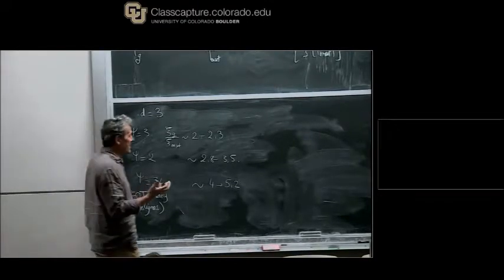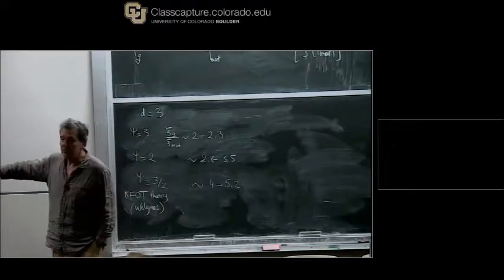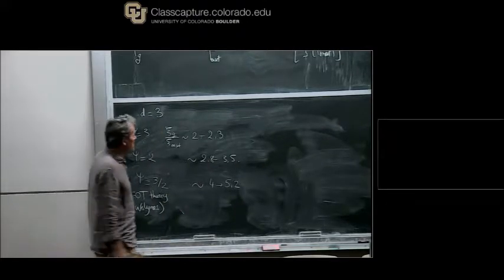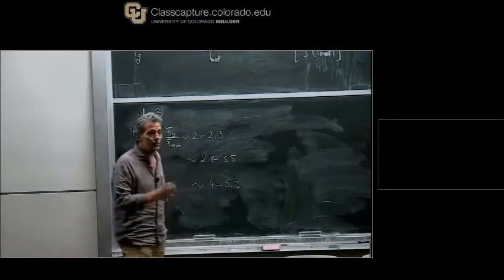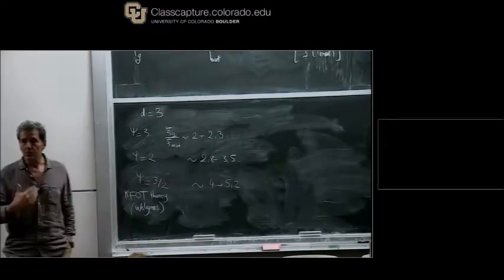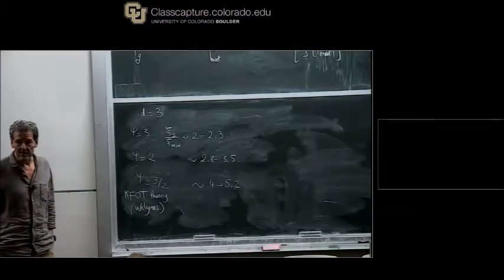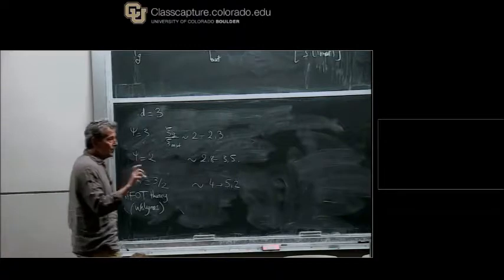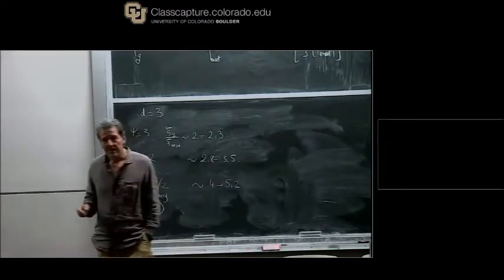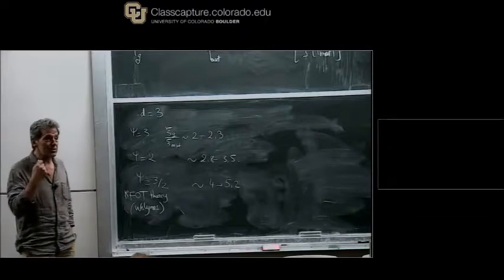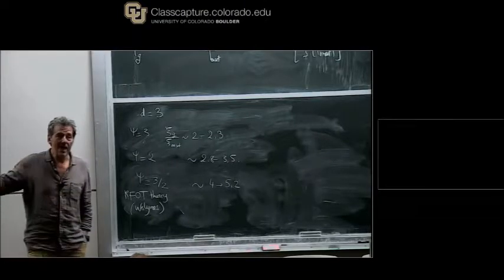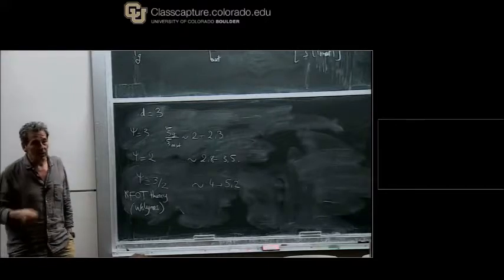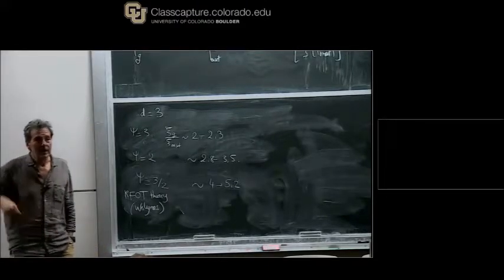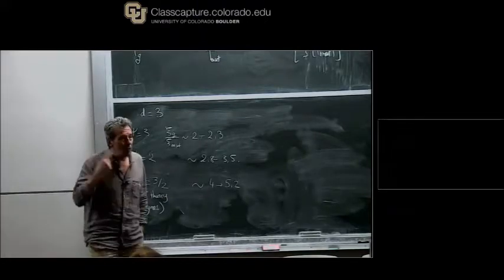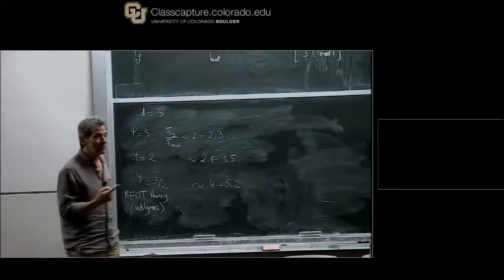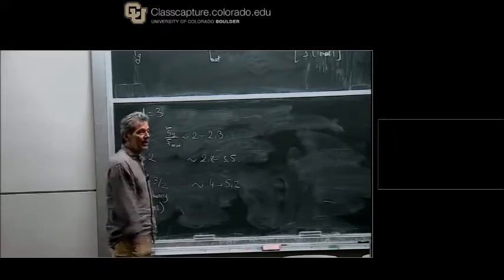So you have length scales. Here I was saying 5 to 10 for those lengths. Here I'm saying, let's say, 2 to 5. And with that sort of change, you could explain the slowing down of the dynamics. So you can take this both ways. That is, you can say, well, okay, if I measure a small length scale while I have a widely diverging correlation length, diverging not for real, just increasing correlation length, well, this is indeed the signature of activated dynamic scaling.